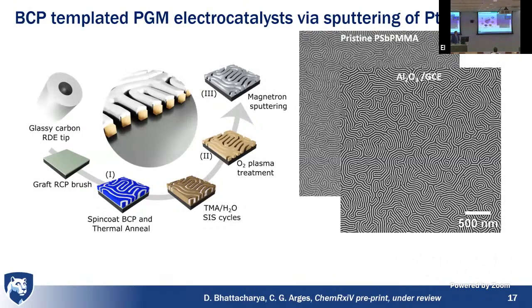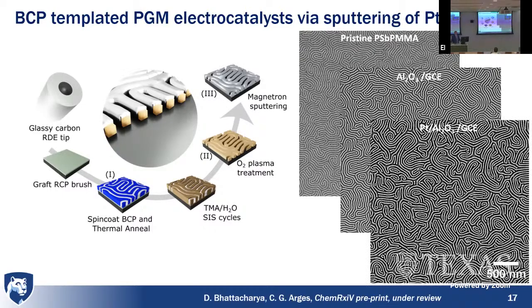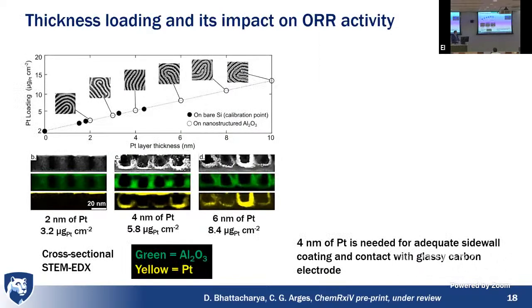This is our alumina structure on the glassy carbon after growing the alumina and then etching away the polystyrene. And then this is after we coat a very, very thin layer of platinum on the surface. So we have our extended surface electrocatalyst now. One of the things my student Deepa wanted to find out was, how low can we go? We really wanted to get to the lowest loading possible, like 1 or 2 nanometers, but I think that was a little